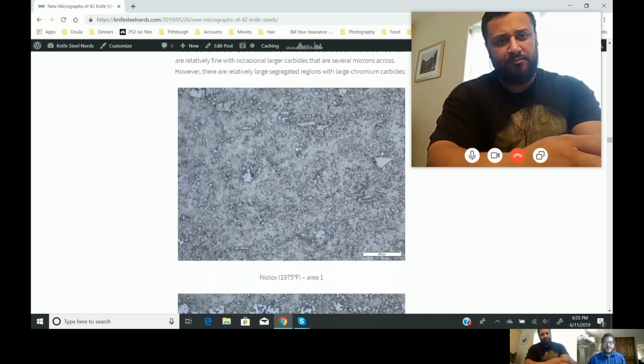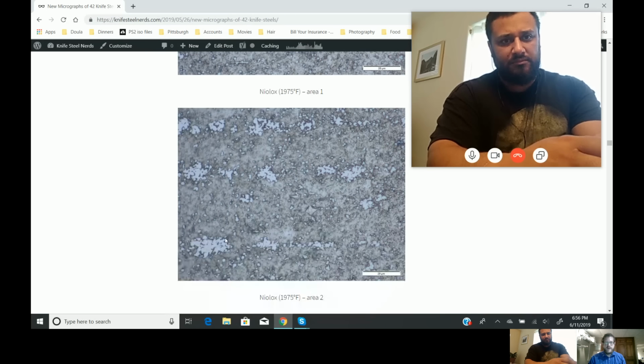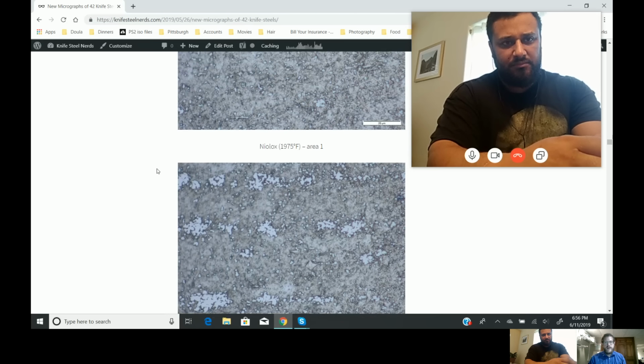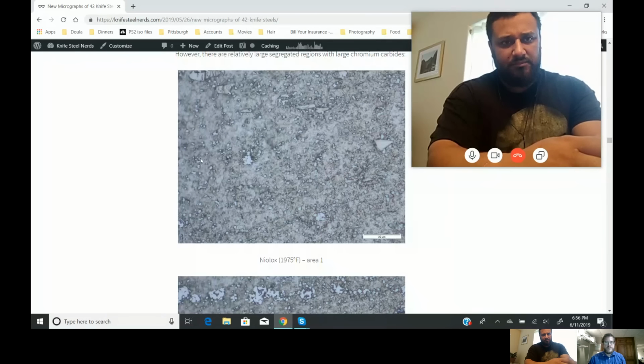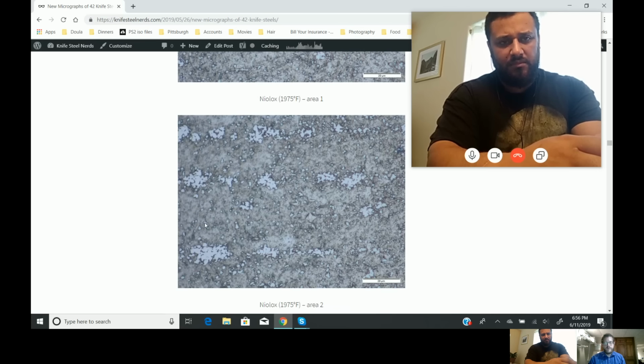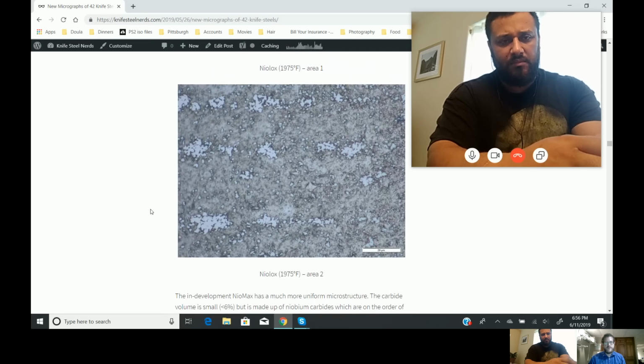Niolox is another one. So this is an area where it's a pretty fine microstructure. It's got some chromium carbides that are bunched up together a little bit, and this angular looking thing is a niobium carbide. But then I found these big areas where there were just tons of very segregated chromium carbides that are much bigger. And so Niolox has kind of an intermediate composition where you'd hope it would have in-between toughness, in between AEBL and an S90V or an S30V. But because of these big segregated chromium carbides, it's kind of similar toughness to the powder metallurgy stainless steels. So it doesn't really offer that in-between properties that you're looking for.